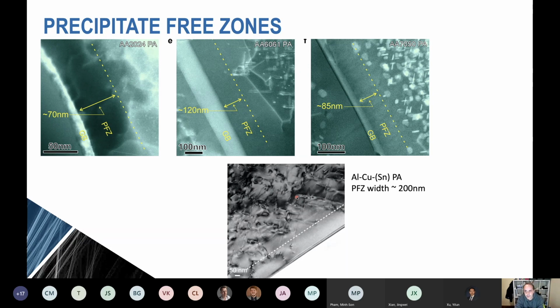And one of the particular damage properties, I'll just show you a few results for now, is the fatigue properties. And for those who work on aluminium alloys, despite us wanting to use aluminium alloys for lightweighting applications in transport, actually aluminium alloys, especially the precipitate strengthened ones, have really terrible high cycle fatigue properties. It's quite remarkable, actually. If you take something like a steel, over a very, very large range of steel grades and strengths, the fatigue ratio for steel, let's say the fatigue strength divided by the UTS, is about 0.5. For aluminium alloys, the same ratio is about 0.3, and the correlation is not very good. And so for the same strength increment that you might get from manipulating the microstructure, your return on investment in terms of improved high cycle fatigue performance is much worse for aluminium alloys. And that's a bit of a problem when we want to use aluminium in transport applications.